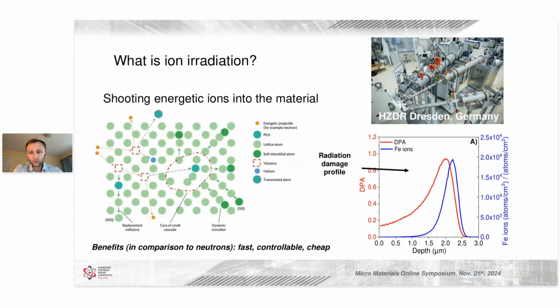How to do that? Well, when you have a material, you can either put it into the reactor core and test how it behaves after irradiation, or you can use ion irradiation. Ion irradiation basically means you are shooting into the material with energetic ions, and by collisions of the atoms, which are caused by interaction with this ion, radiation damage is created. This radiation damage caused by ion irradiation mimics radiation damage caused by neutron irradiation.